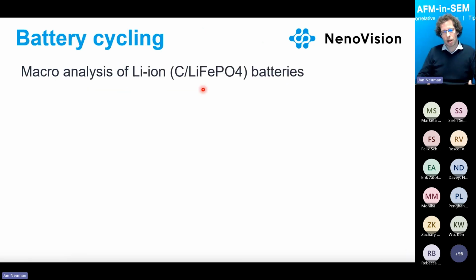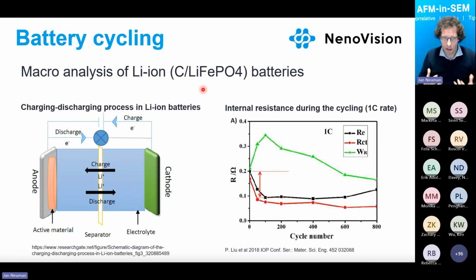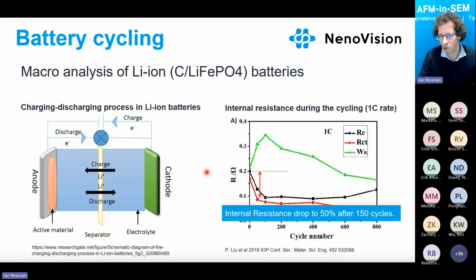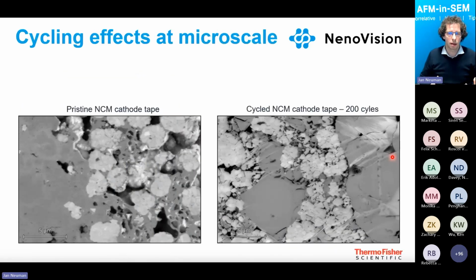Before that, I will jump out to the macro approach and point of view. It's known in the literature that if you are charging the batteries as a whole, and you analyze charging and discharging and cycle the batteries, and you analyze the resistivity of the battery, then after a certain number of cycles after the initiation phase, the resistivity drops. So we see that there is about a 50% drop after 150 cycles. What can be done in the study and how can it be explained on the micro scale?